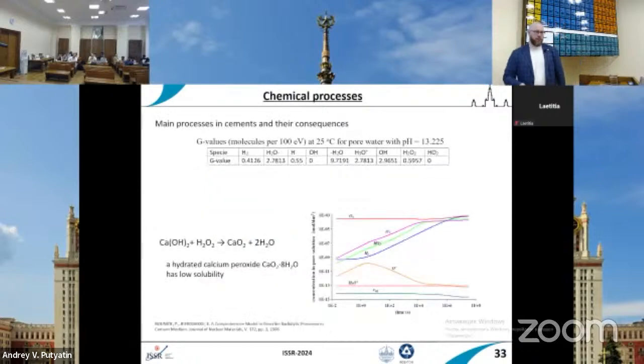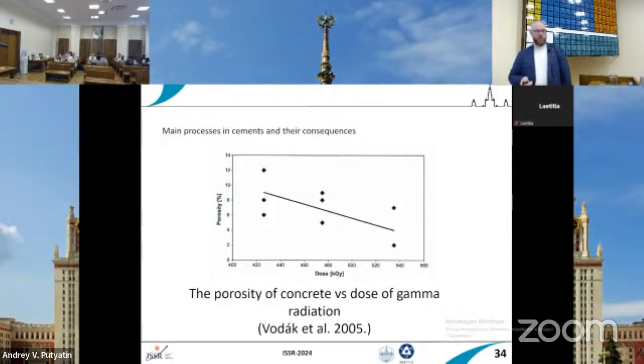And again, we can see there are many works on understanding what is going on in cements. And you can see already obtained these G values. So it's molecules produced per 100 electron volts in the cements. And you can calculate, if you know the dose rate and the time of the irradiation, the yield of the different active species in your material. And one of the products is this calcium peroxide, that will be important for us, as I mentioned previously.